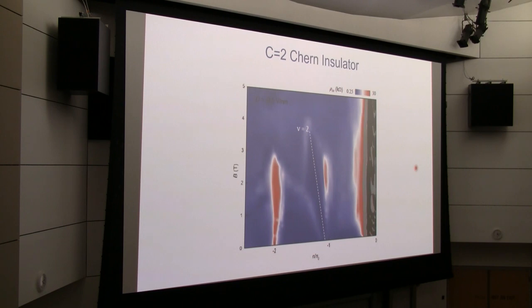And again, we can also see the signature of the same behavior in the magnetotransport plot, where you basically measure the RXX signal as a function of doping on the x-axis and as a function of magnetic field on the y-axis. In a single particle system like graphene, you actually see many Landau fans. In this case, because of the strong correlation, it suppresses most of the quantum oscillation in the system. So we don't see those individual electron Landau fans. Instead, you see a very dominating dispersing line here that has basically 0 RXX, so it's like a quantum Hall state, but it's not single particles. It's a correlated Chern insulator state, and the slope again tells us the quantum Hall number is equal to 2.